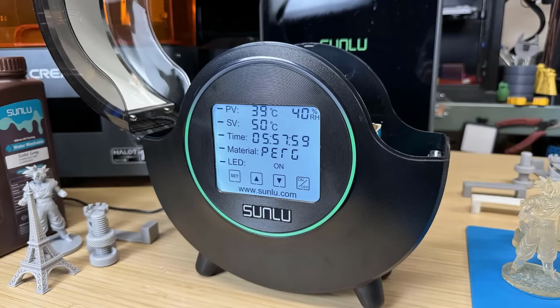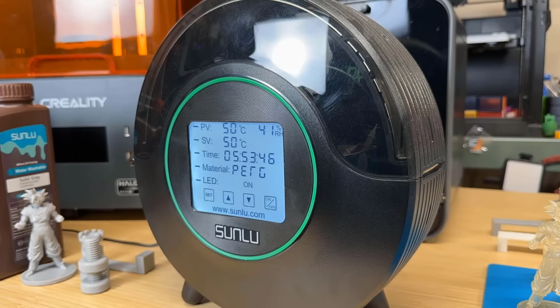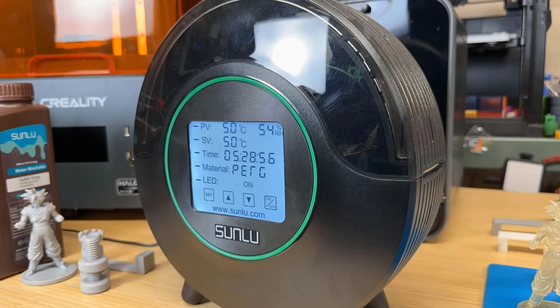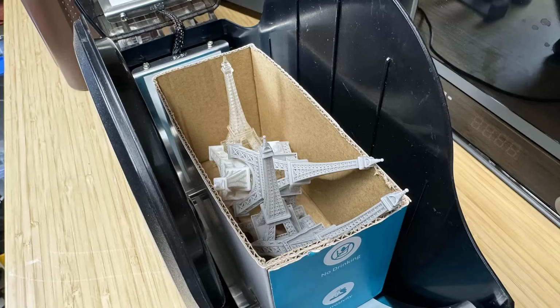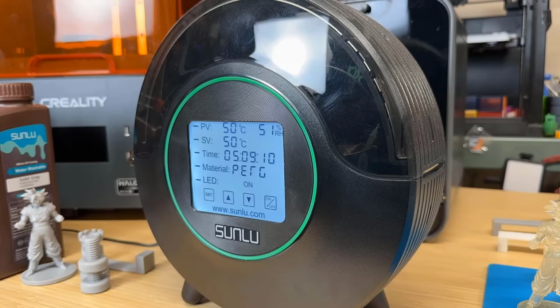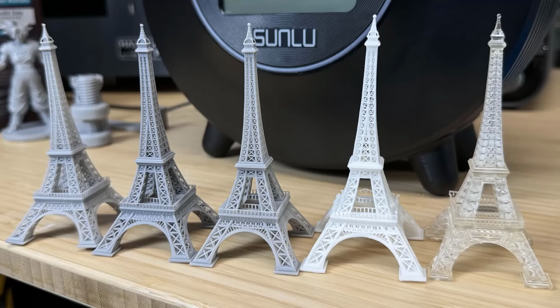Next, I will heat up the Eiffel Tower model. It should be easier to melt or break down under high heat compared to other solid models. Since most resins can resist temperatures of 45 to 55 degrees Celsius, I will start by using the SUNLU filament dryer set to 50 degrees Celsius. I don't want to place the models directly on the heating element, so I will use a box to hold them. After an hour, all of them still look good, with no visible melting or cracking.